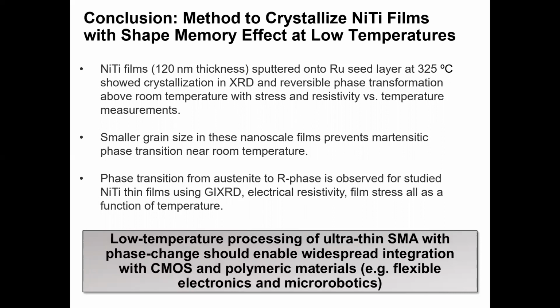the R phase. The temperature-dependent phase transition from austenite to R phase was also observed for these NiTi films using 3 methods, confirming that low temperature processing of SMA films with a phase change should be extensible and enable, you know, greater integration with CMOS and polymer materials. I also list flexible electronics and soft body micro robotics.